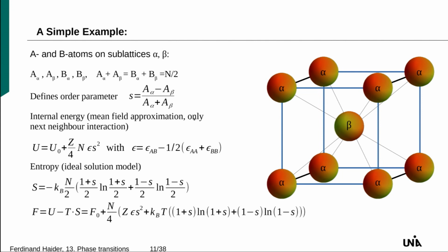In a simple approximation, which I don't write down but it's very simple, you can calculate the internal energy of such an arrangement. Basically, what you do is count the number of AA pairs, BB pairs, AB pairs. And since you have very simple sum rules, finally you end up with this expression here.